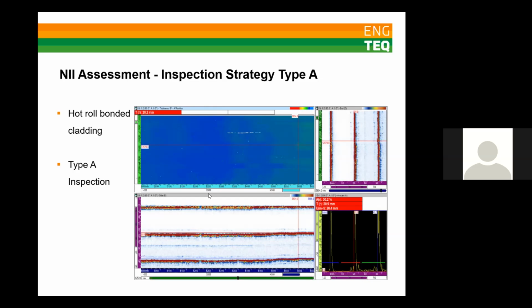on your screens just now, this is an example of a 0 degree method for wall thickness only. So we're not looking for cracking in this inspection. You might be able to see between the outer wall and the back wall, there's a faint blue line, which is the location of the interface between the cladding and the carbon steel substrate. So you can see that there's been no breach of the clad layer in this case, and there's no areas of disbondment or wall loss, and therefore we can be confident that the cladding is still doing its job.